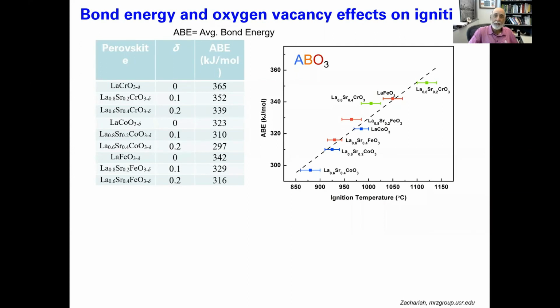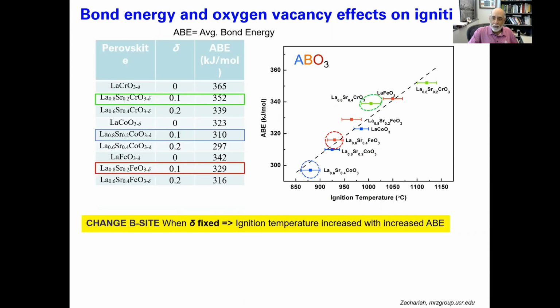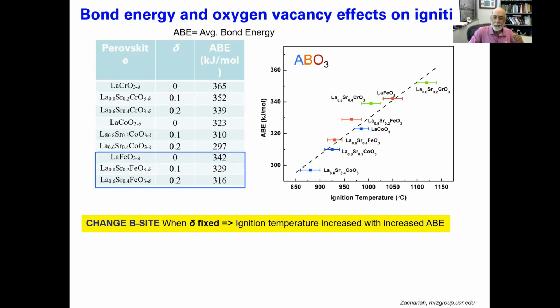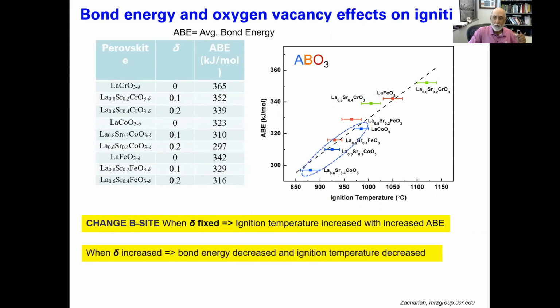We would expect that to be the case, but this is the first demonstration that I'm aware of that ever demonstrates anything remotely like this. So there's this very nice demonstration within classes of reactions, by changing both the B site and the vacancies, that one can get these correlations. So that's the first piece to understand how we can design oxidizers.